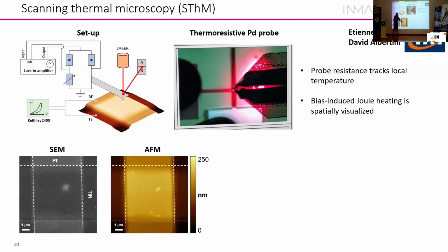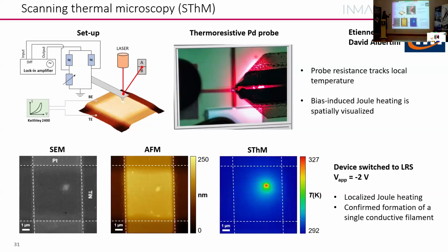This is what we saw by SEM, this white part. By AFM, we see that it has a morphology, so it has a bump. And here is where we really see the filaments. We really see that this is the region that is heating when we're doing the measurements. So it's localized Joule heating, which confirms the presence of this conducting filament.